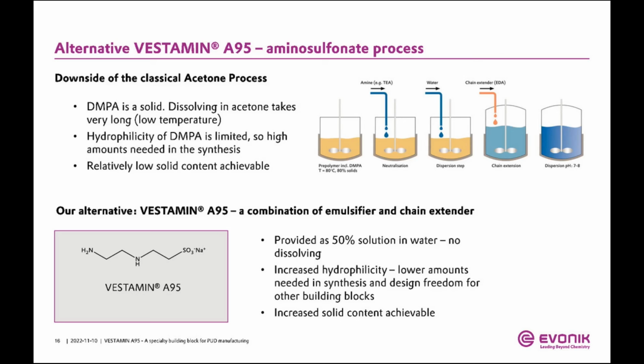If you want to have a more balanced profile and you want to also look at the water stability, for instance, you can go down. A typical ratio, if you compare A95 to, for instance, EDA, the ethylene diamine you use as an additional chain extender, I would say 50-50 also works fine. Less would become difficult, because you would go down so much in solid content that it doesn't make sense anymore. So anything between a 50-50 mix with EDA and full 100% stoichiometry compared to the NCO works.